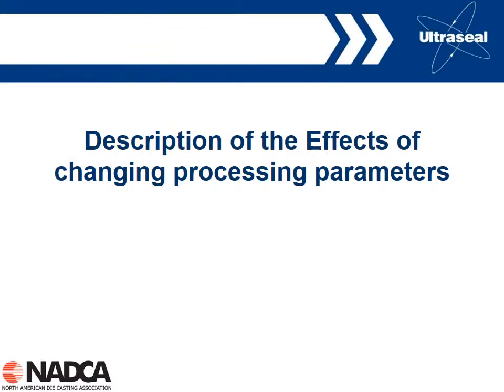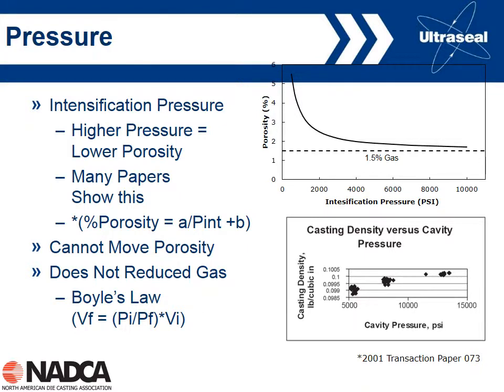So let's talk a little bit about the impact of changing the process parameters and the impact this can have on the porosity levels and distribution. Let's start with a discussion of pressure. This is a great paper from the 2001 NADCA Transactions, paper 073, and these guys performed some experimental work. What they did is define an inverse relationship between the intensification pressure and porosity, i.e., as the pressure increases, the amount of porosity decreases. So, again, no great surprise there. They also defined the equation shown here, where the percentage porosity is a constant divided by the intensification pressure plus a second constant. And NADCA got some data from some other technical papers, determined the values for A and B, and came up with the graph shown here on the upper right.